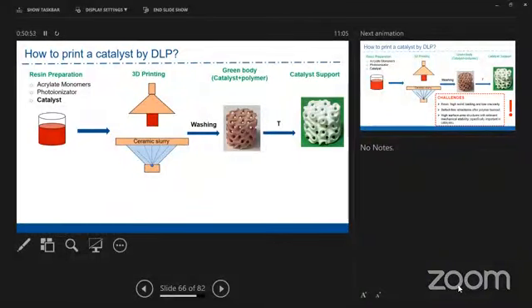We start with the monomer. Either we buy something expensive from the supplier, or we go to the local shop and buy this type of monomers. Then we need to have a photoinitiator. Then we need to have whatever it is, alumina or silica or zeolite. Then the process goes layer by layer. Once again, we start with the mixture of the resin and the catalyst. Then the next step is, after washing, we do calcination, which means that the polymer is burnt away.